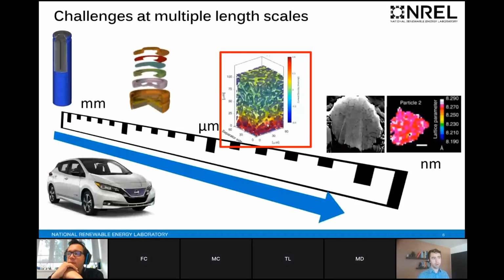Now, overpotential is very important to induce fast charging, and so this is a major limitation in that if we go below 0 volts and apply more than 1 volt of overpotential, it becomes favorable for lithium to just plate on top of the graphite instead of inserting itself into the graphite. And lithium plating is a concern for a few reasons. It's a safety concern. It's a very unstable metal. It reacts very readily with the electrolyte. And also if lithium plates and starts to react with the electrolyte, it very rapidly decreases the capacity of the cell. So a lot of those reactions are irreversible, and this leads to lithium consumption. And so that lithium can no longer be used for charge and discharge.